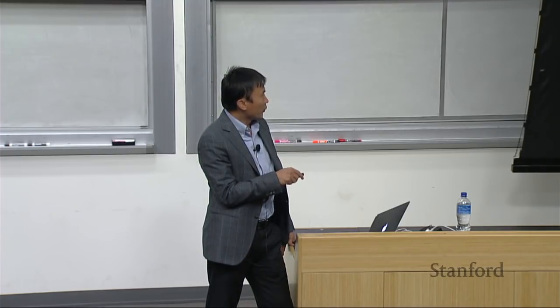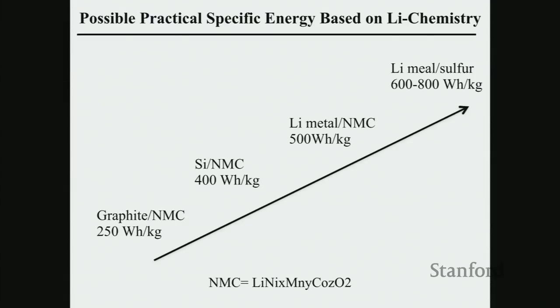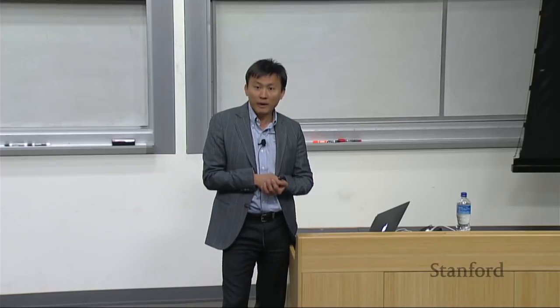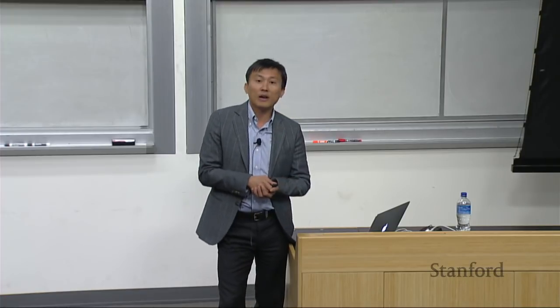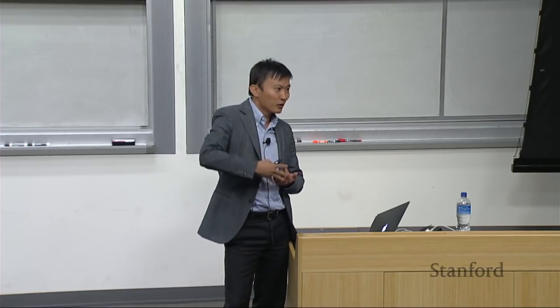And nowadays still graphite combined with a nickel manganese cobalt oxide, here XYZ, different ratios. The maximum you possibly can reach is about 250 watt per kilo. With silicon replacing graphite, you get to 400. And metallic lithium coming in to replace silicon, you might get to 500. And then sulfur replacing NMC, combined with lithium metal, you could reach potentially 600 to 800 watt per kilo. We have chemistry that allows you a runway of 3x in a practical sense. But this could take 10, 15 years in a practical cell before you see this technology coming out.